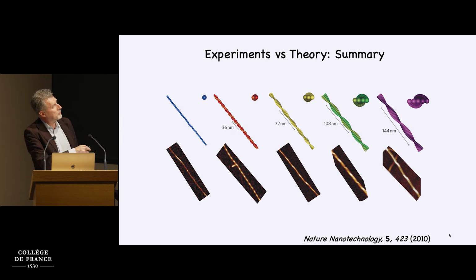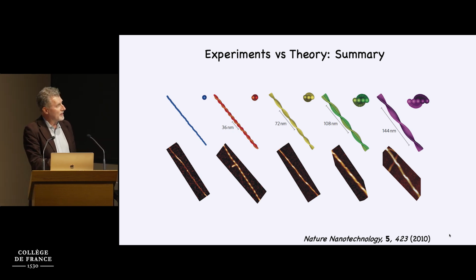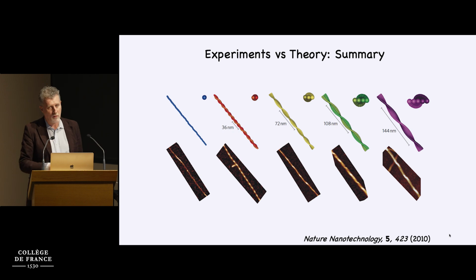So if I would put a histogram here, you would see a log-normal distribution. This is the most crowded population, but you see multi-stranded fibrils. And the beauty of that is that although we have counted up to 11 or 12 protofilaments, the angle, so the pitch over the width, is preserved.